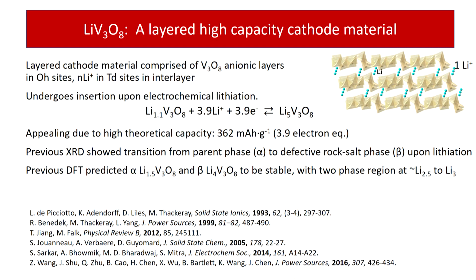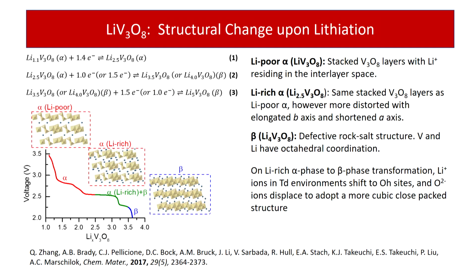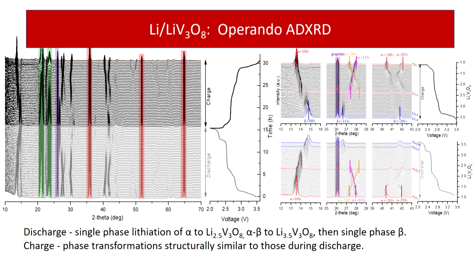I'll move quickly through a new material and then end with some views of some future initiatives I think are important to the battery community as well as society. Lithium vanadium oxide, a high-capacity material with potential of over 300 milliamp hours per gram. It has multiple phases that form: alpha, lithium-rich, and then beta phase. If we track this material using a thin electrode and angular dependent X-ray diffraction, we can track these phases. It tells us what's happening. It doesn't tell us where it's happening.